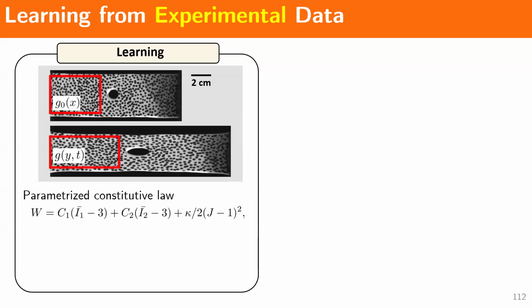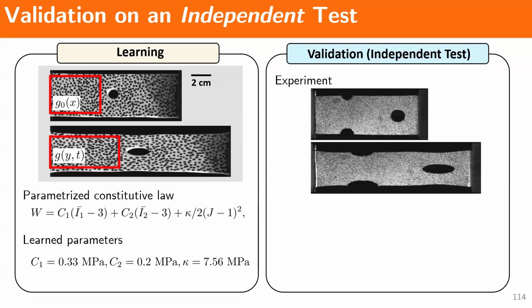Then we assume the following constitutive parameters, and we can run the algorithm, and this leads to some learned parameters for our constitutive form. So this is our model from the learning process from the experimental data. Again, with real rubber, we actually don't know what our model is. We have no idea of the ground truth of the model. So what we can do here is compare our method with the current method that exists out there, which is DIC, because that's the only method that exists.